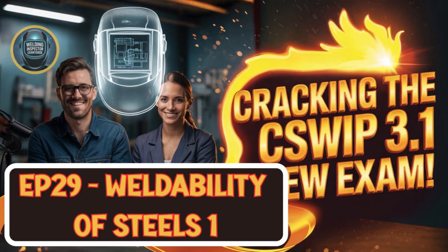First up, this sort of silent, delayed threat. Hydrogen cracking. Yes, hydrogen cracking. Or, technically, hydrogen-induced cold cracking, HICC. Heard of it. Yeah, but you'll often hear it referred to by many names that describe its characteristics, like cold cracking, because it occurs when the weld is cooled down. Makes sense. Or HAZ cracking, because it primarily occurs in the heat-affected zone. The HAZ, that's the part of the parent metal right next to the weld, the bit that gets hot but doesn't actually melt. Exactly that, and it's particularly vulnerable.